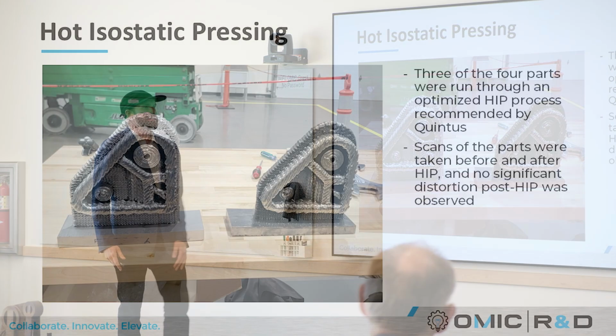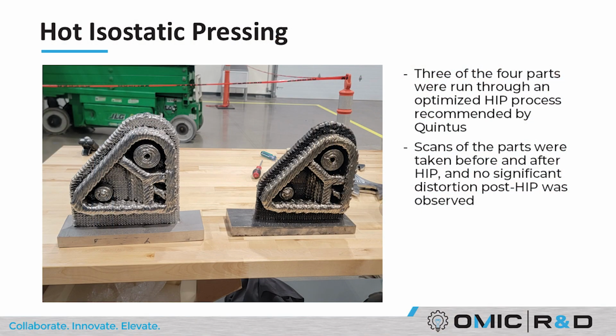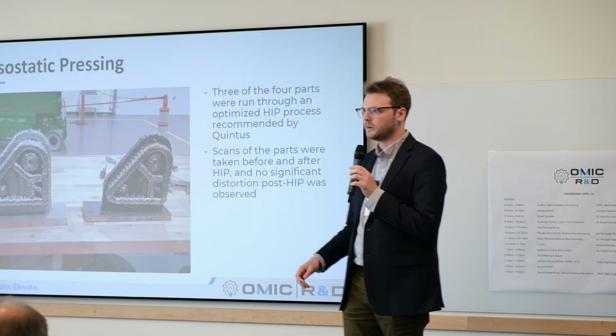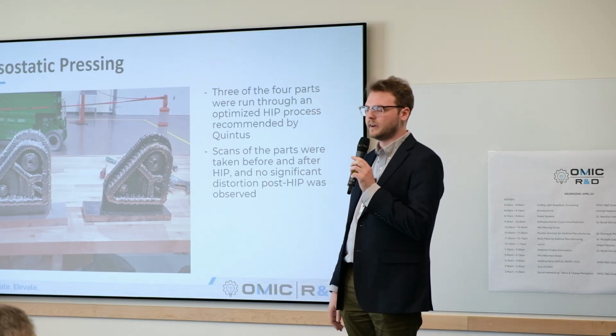So talk a bit more about it. Yeah, three of our four parts were run through an optimized hip process that was recommended by Quintus, that they've seen developing in the aerospace industry. This hip process is to maintain just a little bit of that microstructure that we can develop through additive manufacturing, because it's very difficult to achieve otherwise, while taking out your porosity and still homogenizing the structure. Right. And then pre and post hip scans were taken to see what kind of distortion we were witnessing, and we did not see any significant movement after hipping. So our parts were going in straight and coming out straight, which is nice.